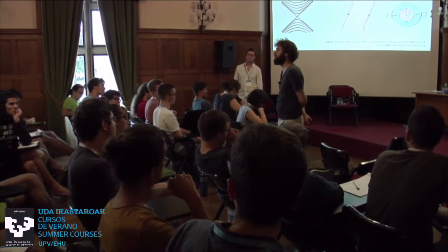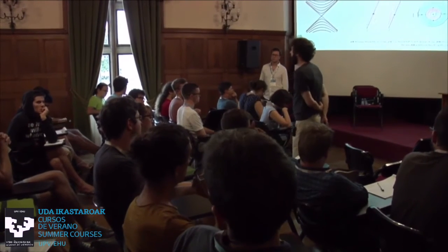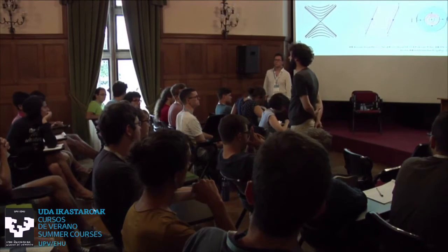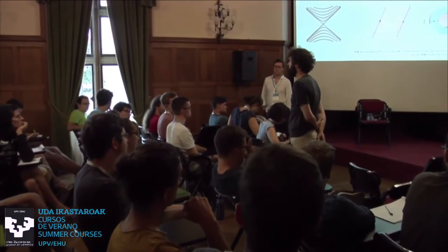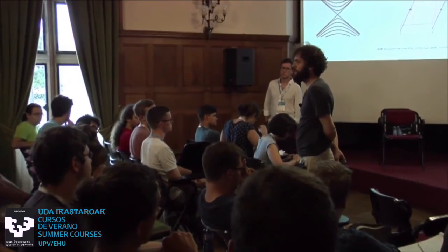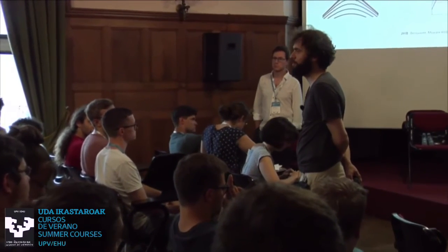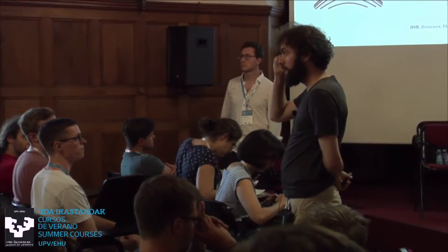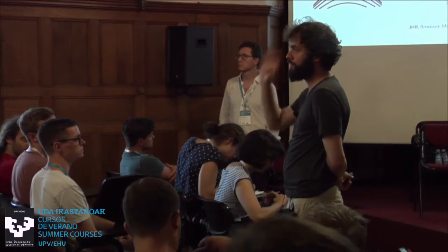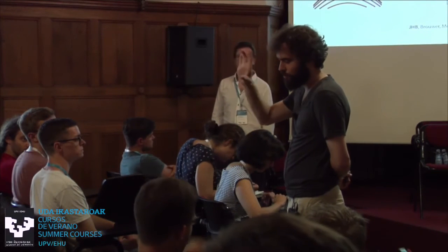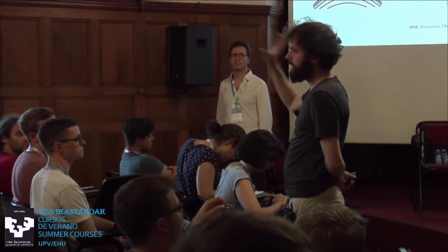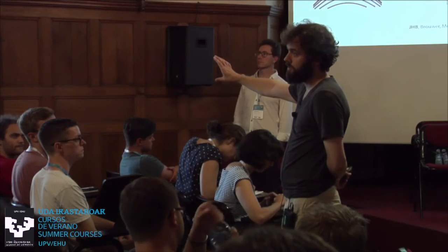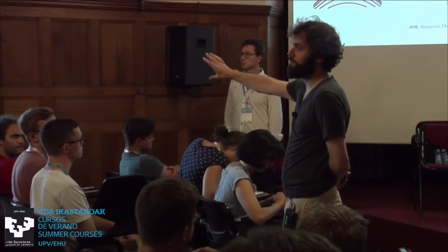So no, that's right. This is a matter of length scale. Strictly speaking, if I keep the circumference of the wire fixed and then take L to infinity, then yes, it will basically always be zero except for a very fine-tuned point. But if I look at experimentally relevant values, for example, a few hundred nanometer circumference and a micron long wire, then you're very, very far from the localizing regime.